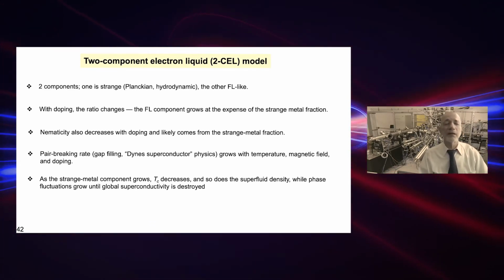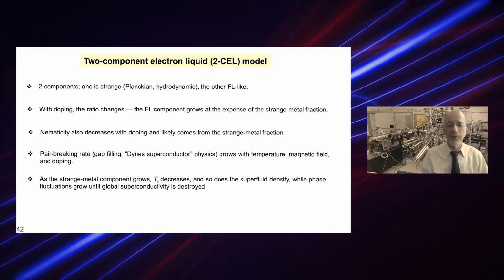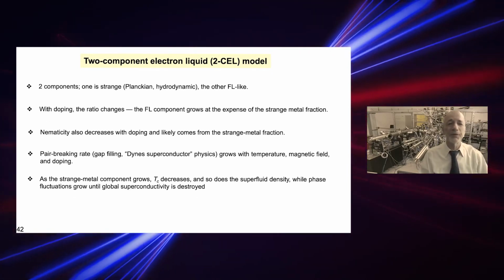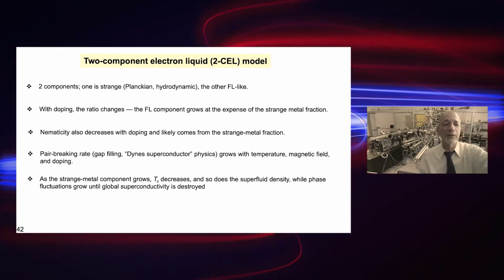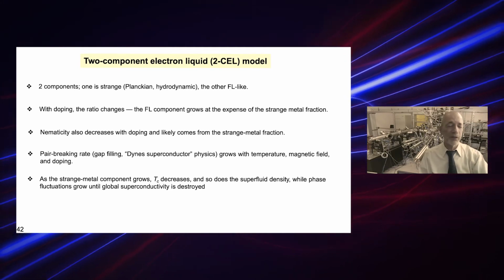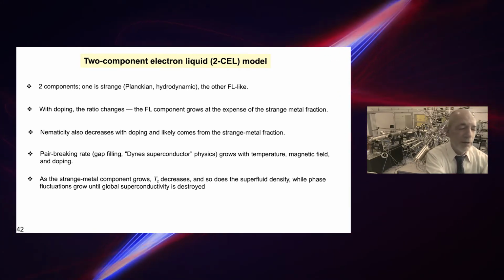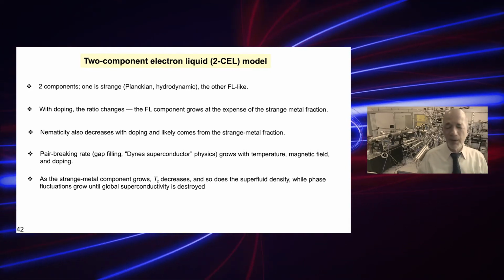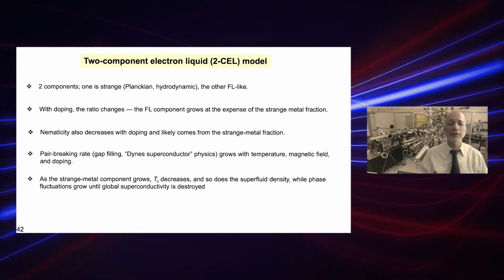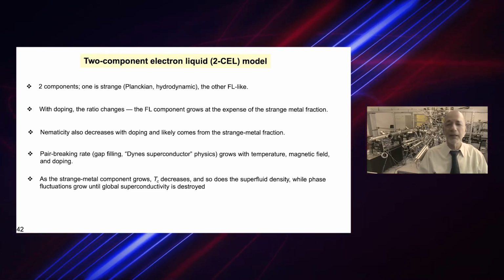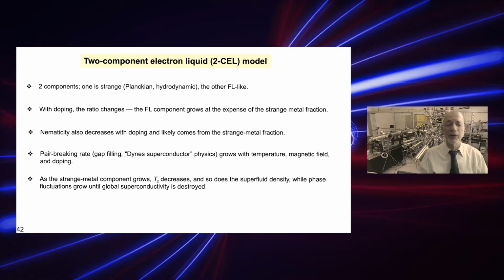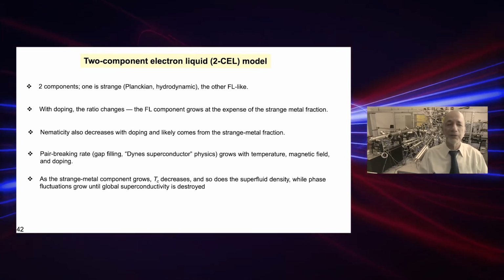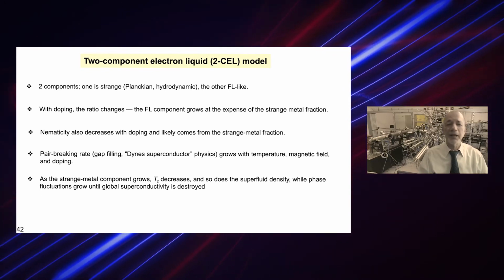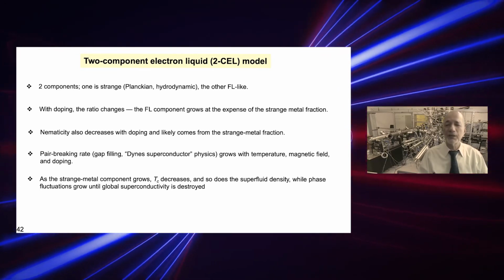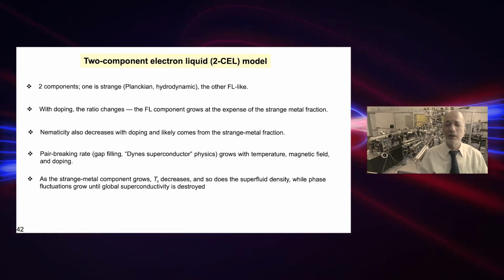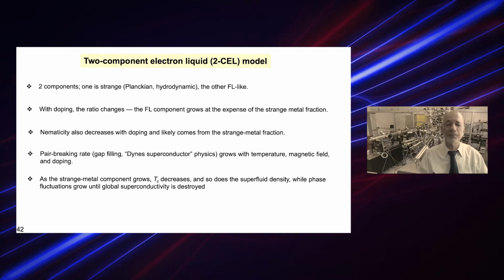This is then my proposal, that actually data could fit better a two-component model, something like a parallel series of two conductors, one of which is strange, showing Planckian or hydrodynamic behavior, the other Fermi-liquid-like. With doping, their nature doesn't change, but the ratio does. The Fermi-liquid component grows at the expense of the strange metal fraction, which disappears at the edge of the dome.